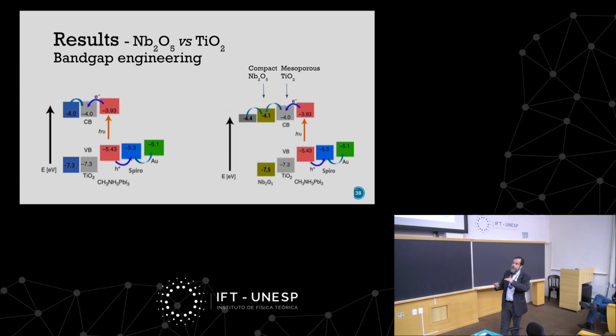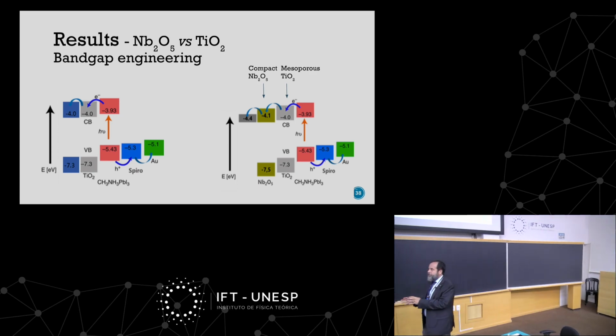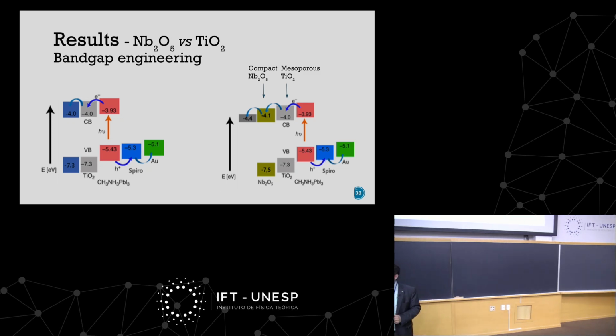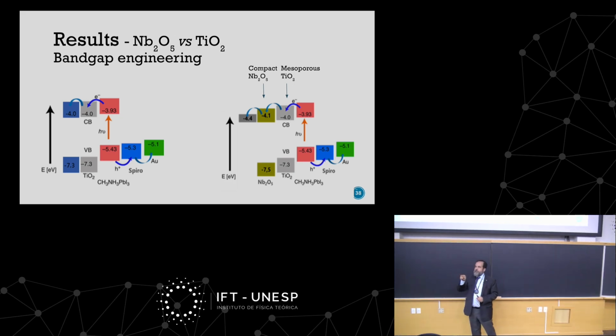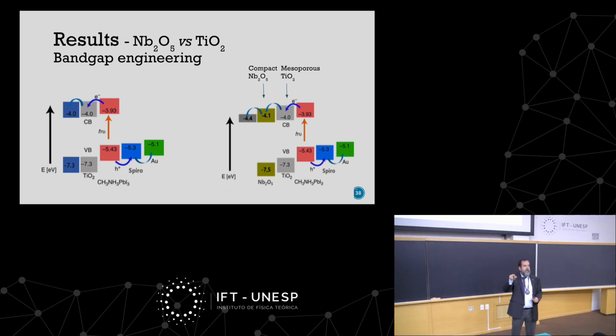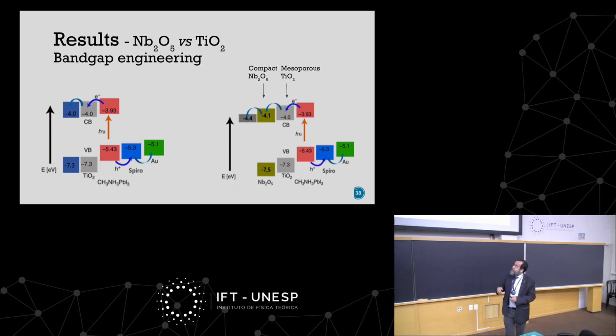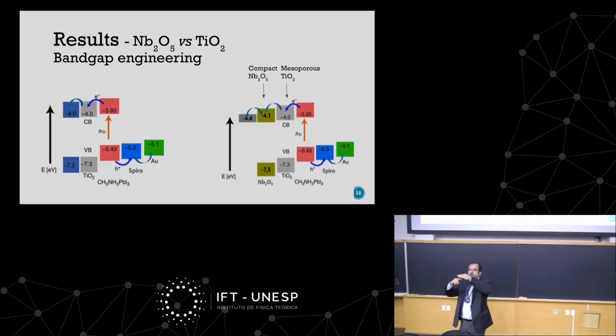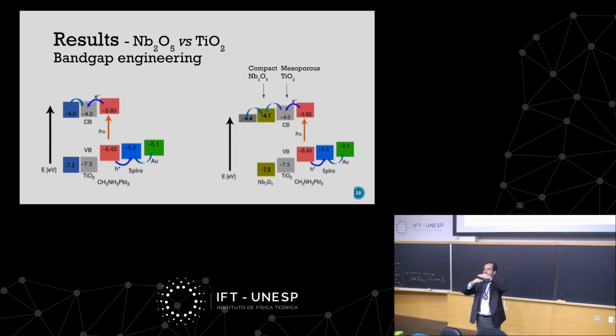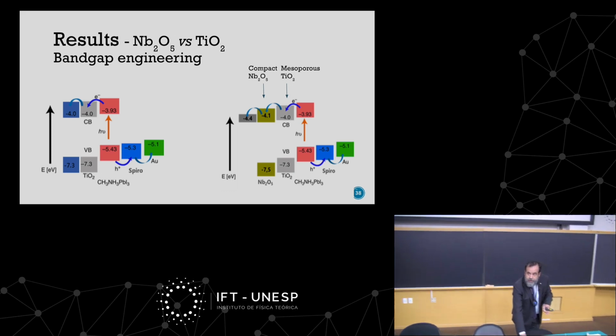While when I have TiO2 as compact and mesoporous, I don't have any step for the electron. So the electrons can stay in the mesoporous part. So they are transferred, but some of them don't go to the contact. They just keep there on the mesoporous part. And because of that, this electron is very reactive. So it reacts with the organic part of the perovskite, that methylammonium, and it degrades the organic part, so that's why it degrades. And at the same time, electrons in this structure, it's like a capacitor. So if I'm keeping charge here, it works as any charge. So I have like a virtual capacitor that is changing with time. So that's why I have hysteresis. So if I go from low to high and high to low, I have changes in the distribution of charge. So I solved two problems with just one simple change in this layer.